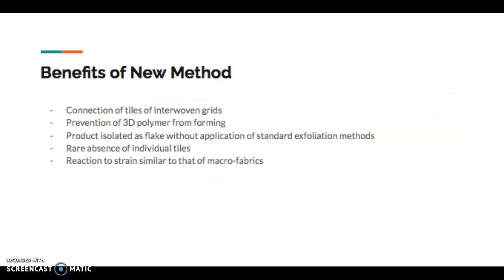The woven ligand strands were able to cover small gaps through reptation, which is slithering movements, reptilian, if you will, within the weave. And so when there were any small gaps, such as an absence of an individual tile, which was rare, the woven ligand strands were able to cover it up and make it even less noticeable. And because of the woven architecture and long-range order, which is regularity over distances greater than just 1 or 2 atom spaces, so compared to crystallization, it's a much larger region,